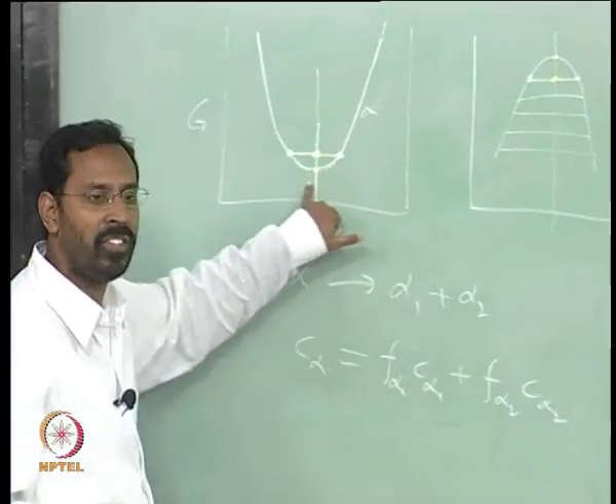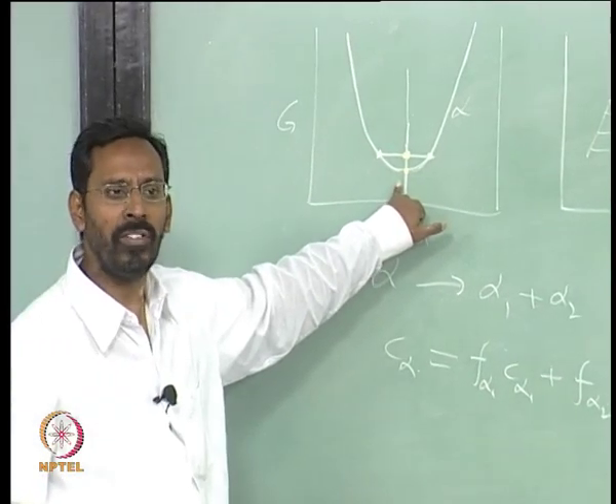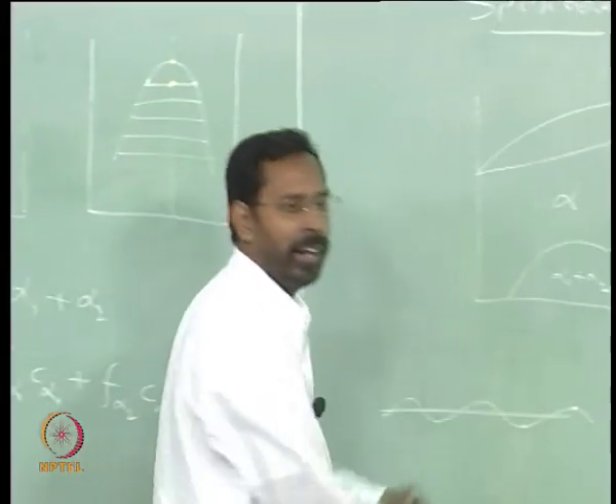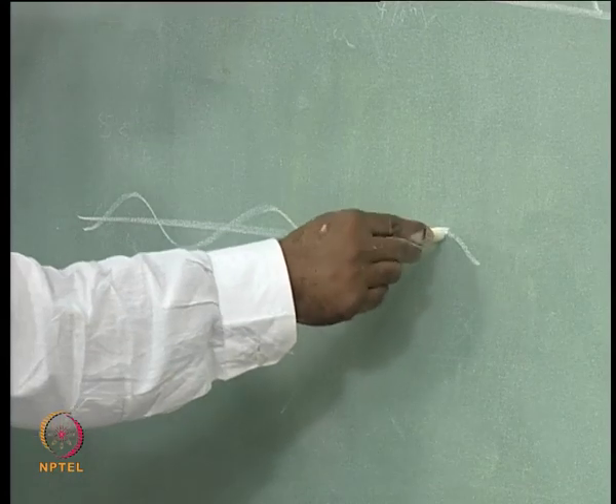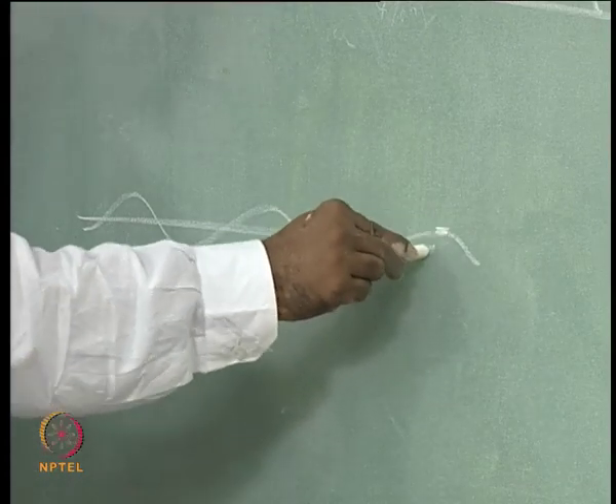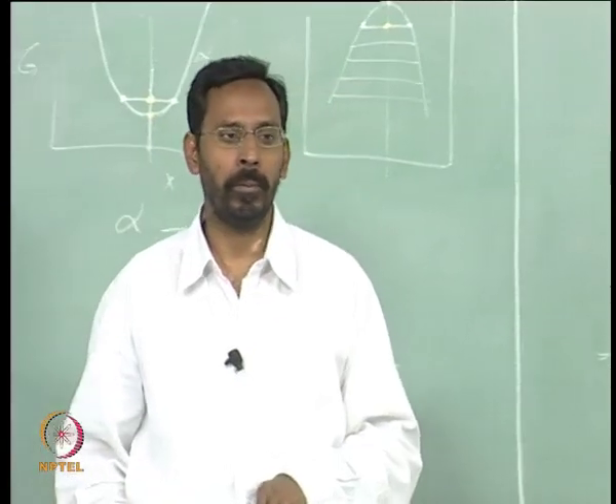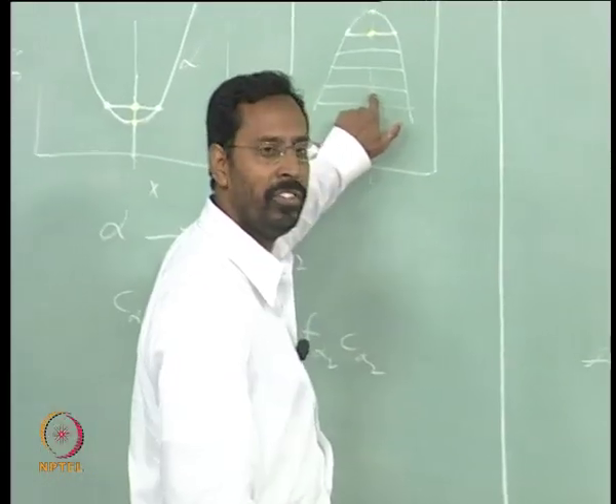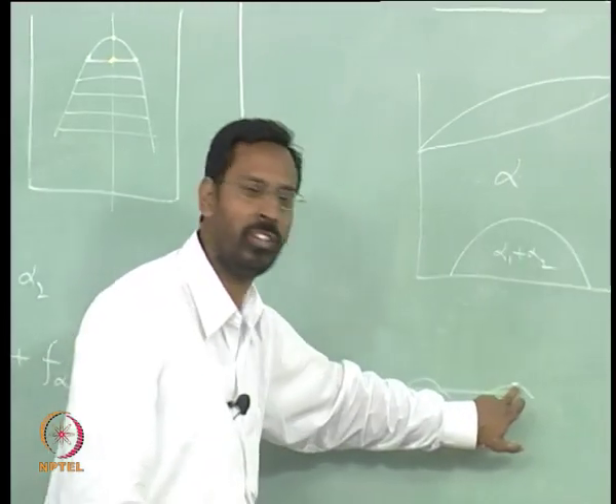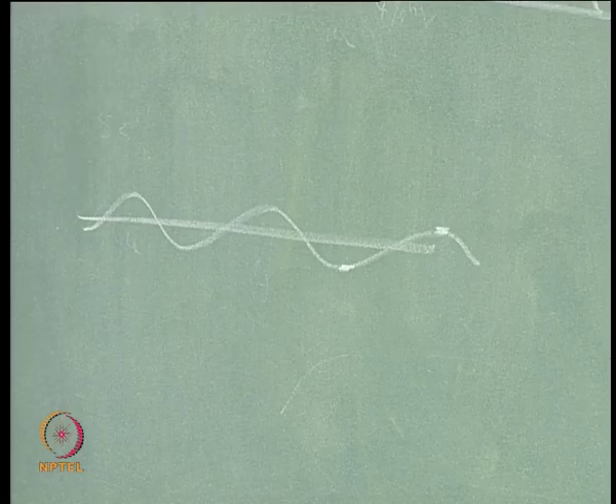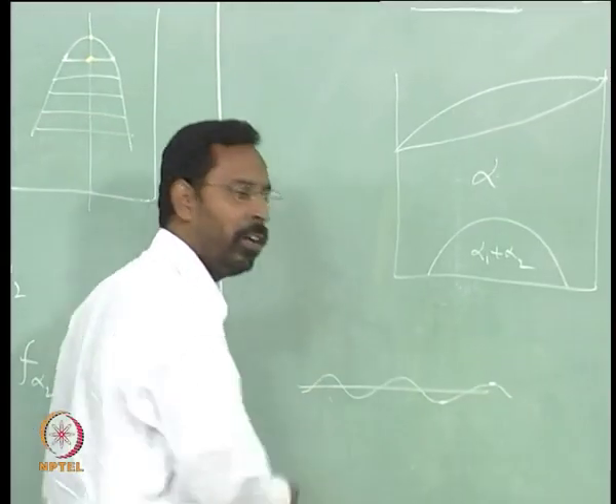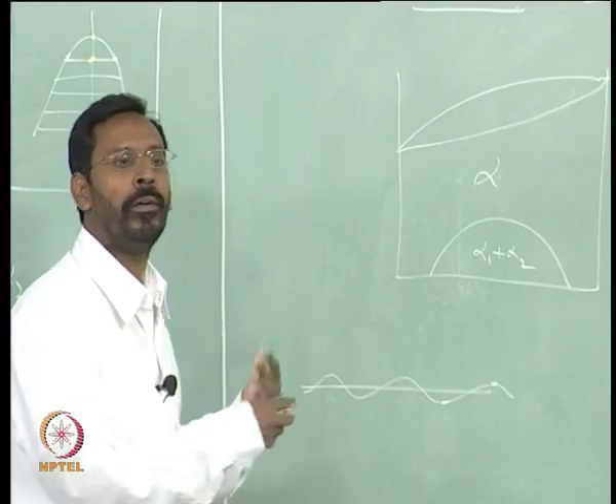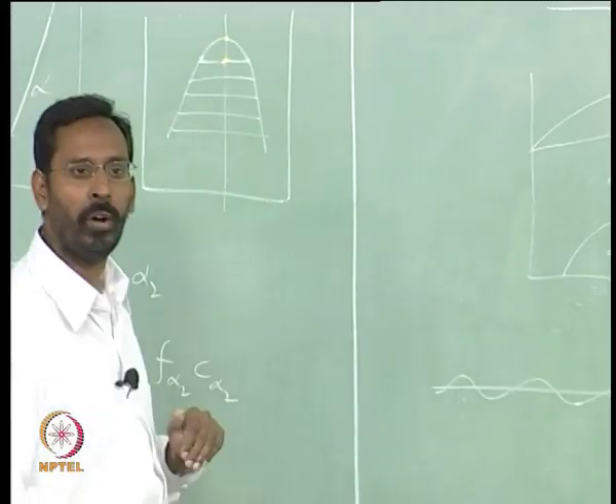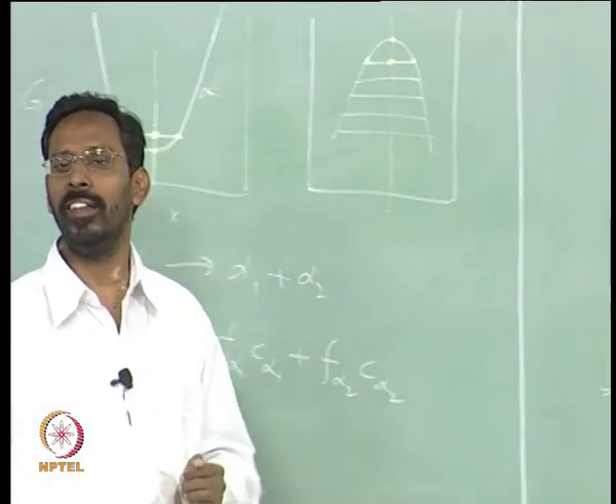But if that happens in this alloy, it will not be stable. The excess atoms will come back and join the alpha, so that again the alpha will have the same composition. Whereas in this kind of situation, once the atoms come to this state, they will not go back, because that is a stable situation. And now this particular thing starts growing. Why does it grow? Because by further growing you will have a further decrease in free energy.